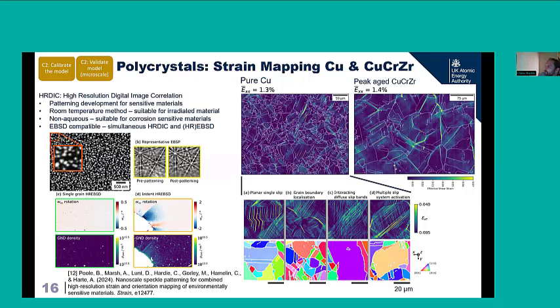And this is just some example data sets on pure copper and copper chrome zirconium. And it shows how the deformation isn't simple, and the deformation mechanisms that we need to represent in our models are quite diverse. And here's just unpicking a few different mechanisms here at the bottom: planar single slip, grain boundary localization, and potentially sliding, and so on.